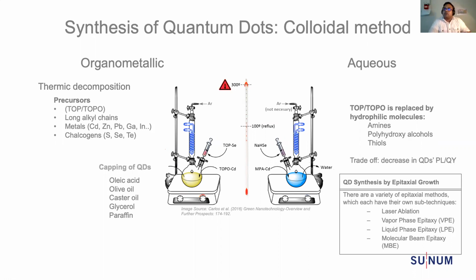There are two ways of controlling the size of these nanocrystals during synthesis. One is to take control of the precursors, and the timing of injecting the precursor into the medium is a critical task. Timing, temperature, and reaction conditions are the critical factors that govern the size of nanocrystals. The organometallic method of synthesis is essentially a thermal decomposition reaction, which decomposes, nucleates, and then these long chain alkyl groups go on and cap the surface of nanocrystals.